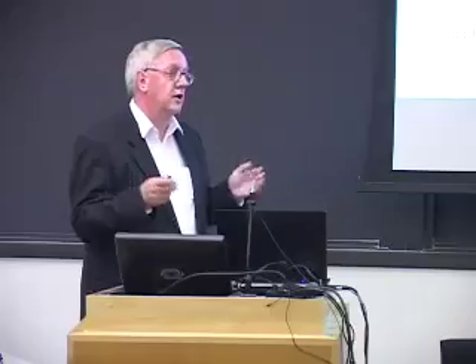And what happens is illustrated here. If you look on the left-hand side here, it might be optimized for direct sunlight. And then when you get diffuse sunlight, the efficiency can drop by about half. And that's something that you often don't hear about, but is accepted if you talk to the people in the area. With our designs, you really play to the maximum performance of all the cells under all illumination. So you don't lose the efficiency you would with differences in light. That also extends to differences in temperature and other performance conditions.